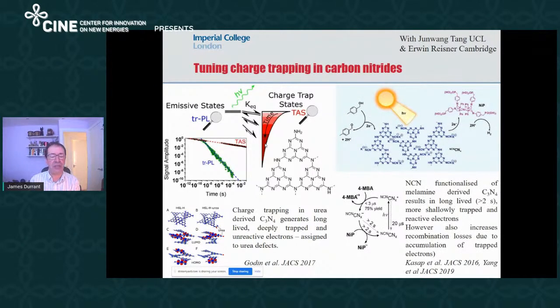But if you change the synthesis of the carbon nitride, so not from urea but now from melamine, and you treat it on the surface, the defects are no longer urea defects but NCN defects. And these NCN defects function as shallow electron traps, and now the electrons are able to go on to drive the catalysis of proton reduction. And so you can trap electrons in this material for seconds and still use that to drive the reduction of protons to hydrogen. The only challenge here, of course, is that now you're starting to accumulate lots of electrons in the system, and these electrons themselves cause recombination, which is a study we've been looking at recently.